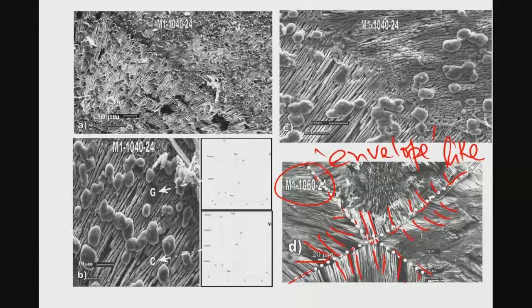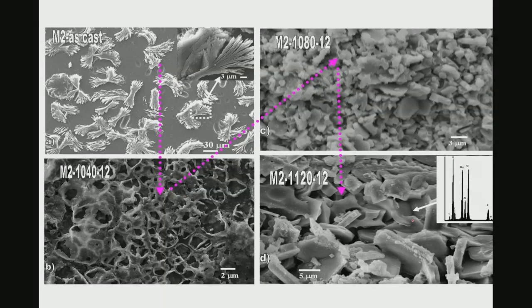This kind of morphology is indeed different from what I described in earlier slides, where I showed cabbage-shaped crystalline morphology or star-shaped morphology. Compared to that, this is indeed different. The other interesting thing you notice here is that the stacking of this rod-shaped crystalline morphology is very dense. It is not dispersed in the microstructure as you have seen before, but a very dense straw-like morphology, and this dense arrangement of crystals in the glass matrix would give rise to better mechanical properties, which we will see in some of the next slides.